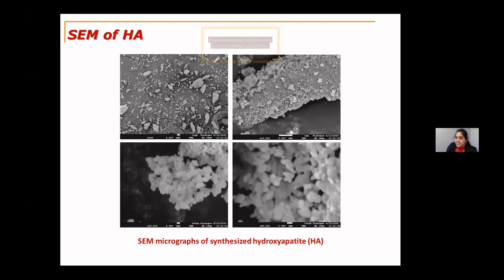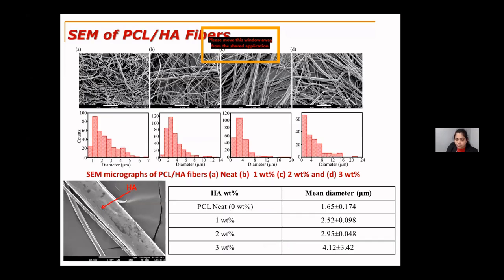No, we did not check thermal conductivity, because, as I said, the polycaprolactone has a low melting point of 55 to 60 degrees centigrade. That is the reason I chose to do the mechanical testing as well as the other testing at room temperature, because heat might melt the polymer nanofibers. However, when I did the DSC, differential scanning calorimetry, I ran that test from negative 80 to 80 degrees centigrade, twice, in a heat, cool, heat cycle. From the DSC results we saw that the enthalpy of the melting endotherm increased while infusing the nanoparticles.